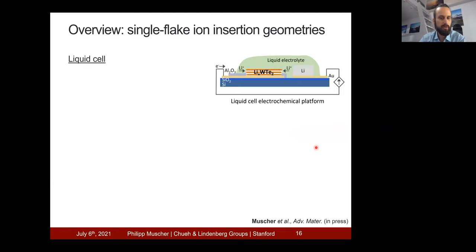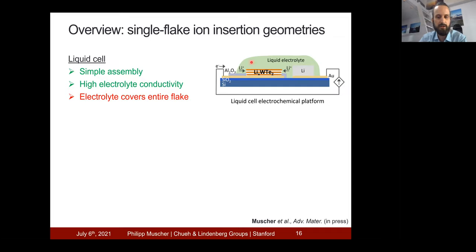So in my work, I'm using two different ion insertion platforms. The first one I showed you already, it's based on liquid electrolyte. It has the advantages of simple assembly, and the liquid electrolyte has very high conductivities. However, it can be a disadvantage that the liquid electrolyte is covering the entire flake, because, for example, if we come in with a laser beam to study this material, the laser beam will have to go through the electrolyte, which will give us noise in our experimental signal, and the electrolyte might also degrade.